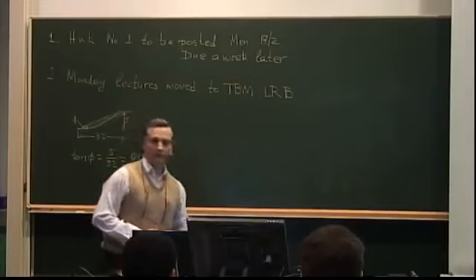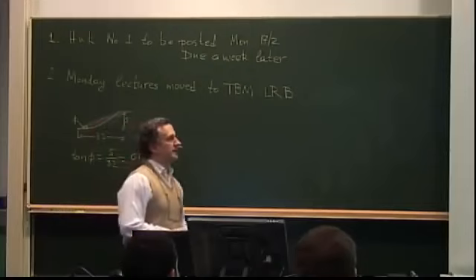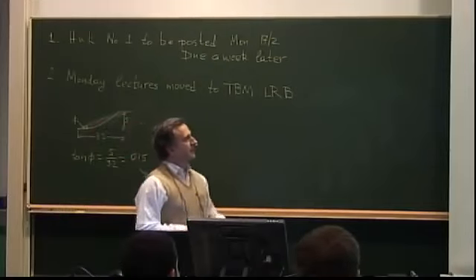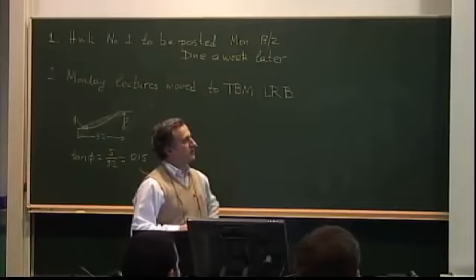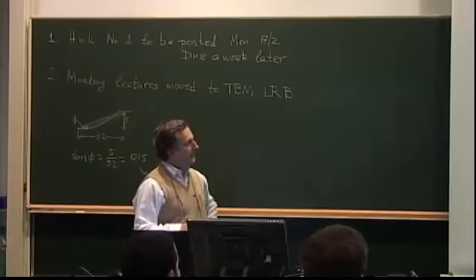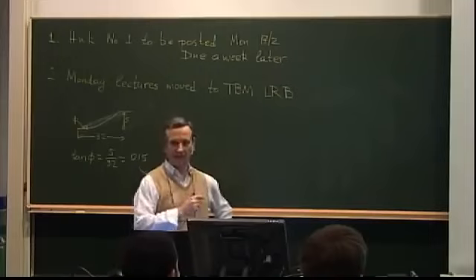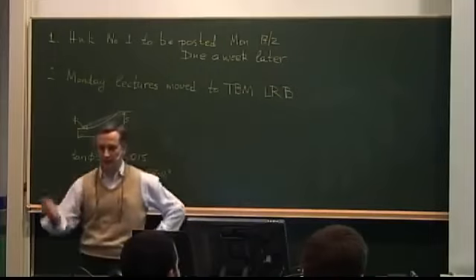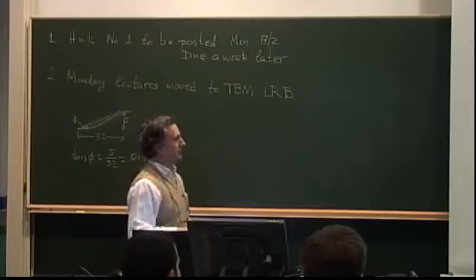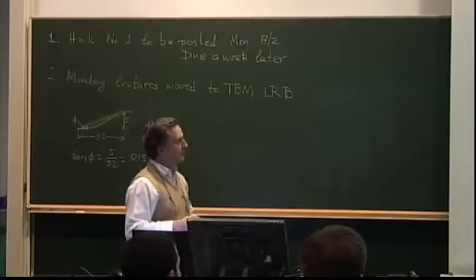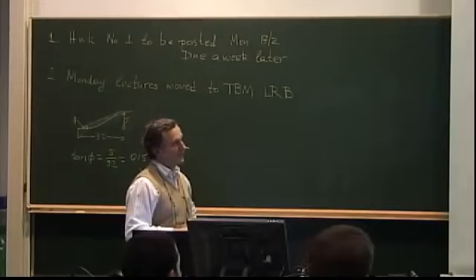If I have pure tension, I can show that most criteria, and this is an example here, will give me about the same predictions. So this is my angle theta for a laminate that's 0, theta, minus theta, symmetric. The reason this laminate is selected is because it has very peculiar failure behavior. And the gentleman working with me these days has actually created this, which shows the failure load on the y-axis as a function of the theta angle, as predicted with 3 different criteria: Puck, the maximum stress we just saw,